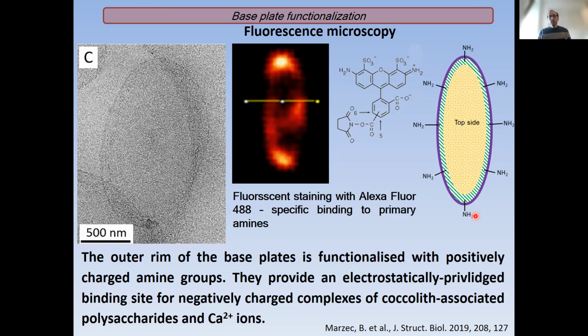So that means that we don't need any specific macromolecular recognition, as it was called then. All we need is favorable electrostatic interactions between the polysaccharide and the nucleation sites on the base plate. And that can be enough to drive the polysaccharides and the calcium ions to the nucleation site. That is essentially the first clue, the chemical composition of the nucleation sites on the base plate. So that is already giving us a clue of what's happening here.